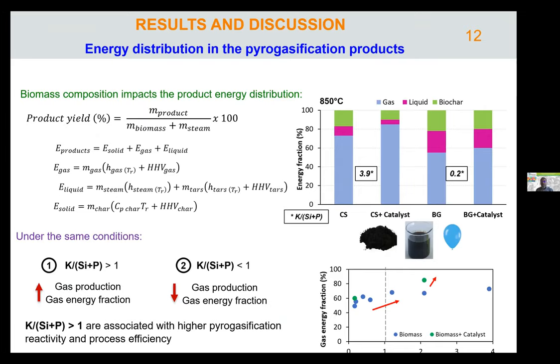And let me show an example of result. If we pyrolyze those components and we see the gas production efficiency, there's a product yield calculation here, and we use the mass of product, it's a kind of efficiency we calculate, right? And you can make an energy balance, using the high heating value and the enthalpy, to determine the fraction of each component of the pyrolysis. What it shows here, you can see in the graph, I'm presenting energy fraction versus the amount of inhibitors, which are K by Si plus P here.